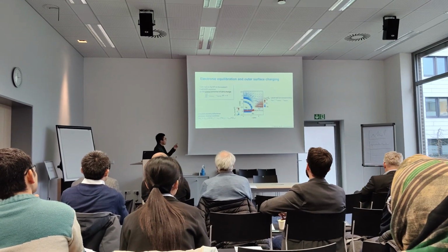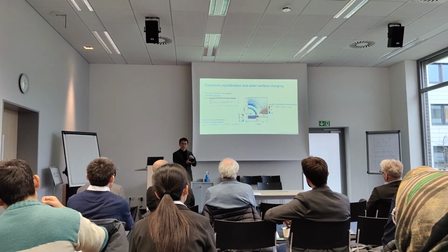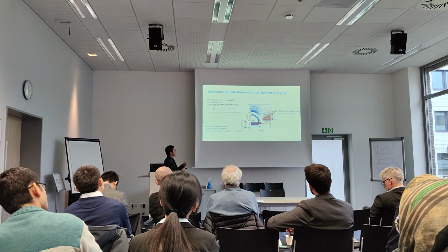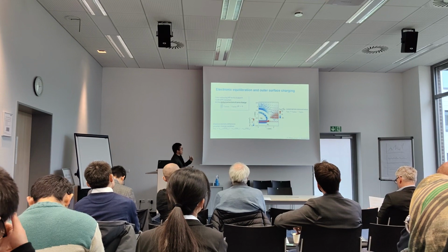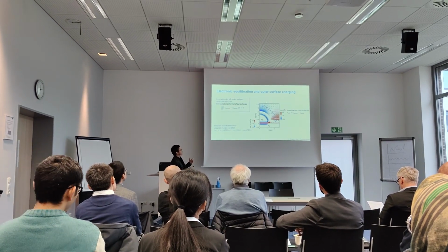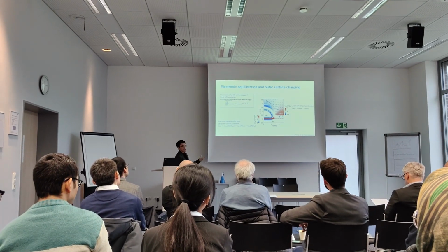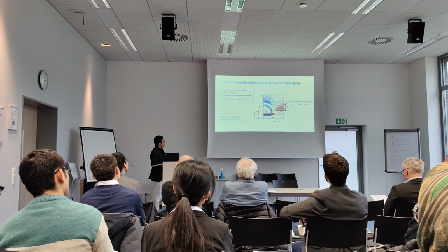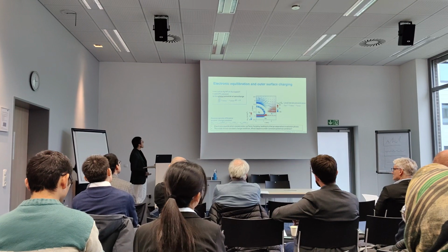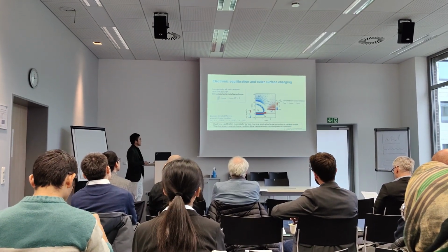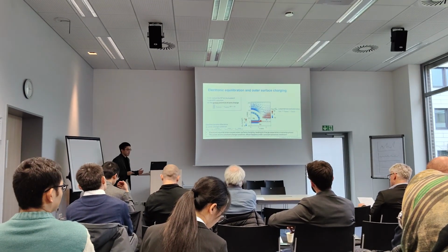So this figure illustrates that once we put the nanoparticle on top of a support in electrolyte, in its fabrication process, there is simultaneous electron redistribution across the system. There's more positive charge left here, more negative charge here, and it creates an electric field surrounding the heterogeneous surface and creates this charge separation in the solution phase. Well, here's a short conclusion of this slide. This slide shows the constant charge condition. What happens under constant potential condition? What happens when we apply a certain potential to this system?